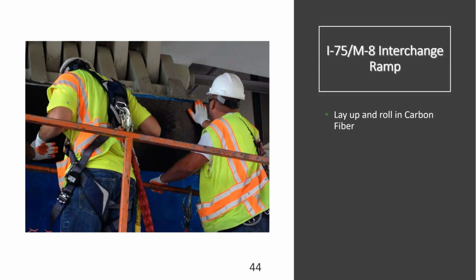While the saturant was still wet, any ends that we had needed to be lapped 4 to 6 inches, depending on the design requirements, the fabric thickness, and what the manufacturer recommended. After the fabric is hung, we used a rib roller, rolled across the surface of the fabric in the direction of the fiber, helping to remove the air bubbles. The rib roller also presses in the fibers to help ensure they are fully encapsulated in the epoxy. The fiber should be rolled until the saturant starts to bleed through the fabric.